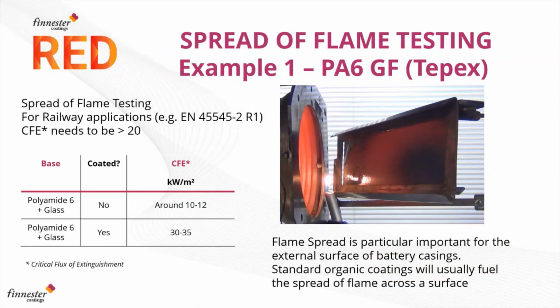I mentioned earlier, not just thermal runaway, but also looking at flame testing and looking at spread of flame is an important property in these materials. So here we have a picture that shows how we do that in our laboratory. We have this cone calorimeter, but we actually run it in a different configuration to normal. We run it in a vertical configuration, and we look at how quickly a flame will spread along the panel